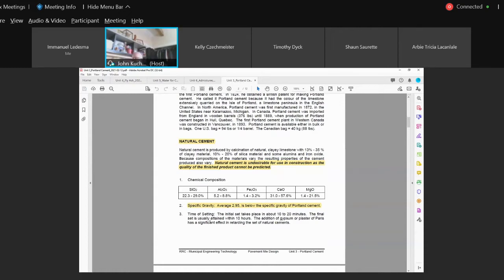We're at 3.15, it's about 2.93, okay. The final set is usually attained within 10 hours for natural cement—ours can be around that also. We can start cutting concrete pavements, with the GU cements, anywhere between 5.5 to 6 hours, which means it's not final set, but it's setting up enough to support weight. But the initial setting time, 10 to 20 minutes, that's fast, okay—you're going to lose your plasticity, you're going to lose your workability. So again, natural cements are not ideal.